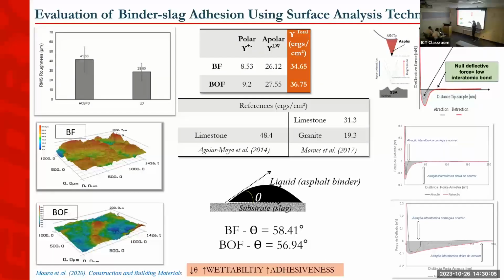Talking about the contact angle, we saw that the BOF showed a little bit lower angle. We can relate that the lower the angle, the better the wettability, and the better the wettability, the better the adhesiveness. It was a little bit lower than BF, but still not so different as to justify what we found.